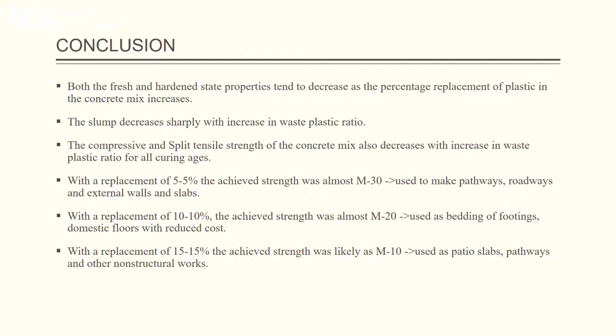The compressive and the split tensile strength of the concrete mix also decreases with increase in waste plastic ratio for all curing ages. With a replacement of 5%, the achieved strength was almost M30, which would be used to make pathways, roadways and external walls and slabs. With a replacement of 10%, the achieved strength was almost M20, which was used as bedding of footings, domestic floors with reduced cost.